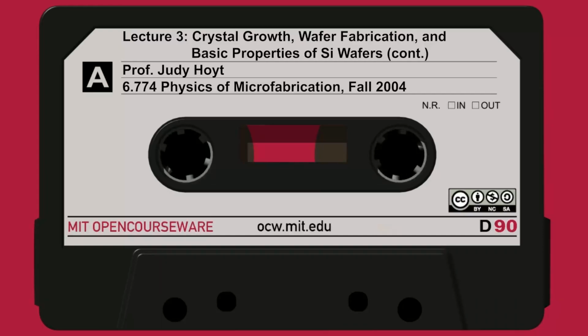So let me just summarize what we talked about, a wide range of things. We talked about native point defects, these vacancies, interstitials. They can be either neutral or charged. The charged defects obey the same statistics as shallow donors and acceptors. So as we move the Fermi level and we dope the crystal N-type or P-type, I can change the concentration of these defects. The good thing, though, is they're still low enough in number that I don't need to use them when I'm calculating the Fermi level position. So that makes it easier.